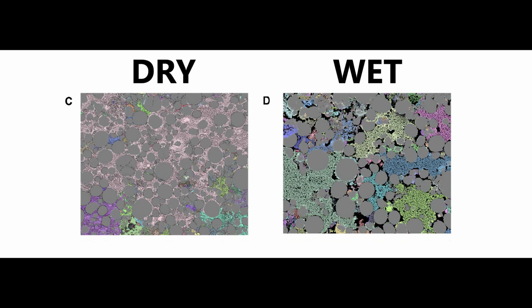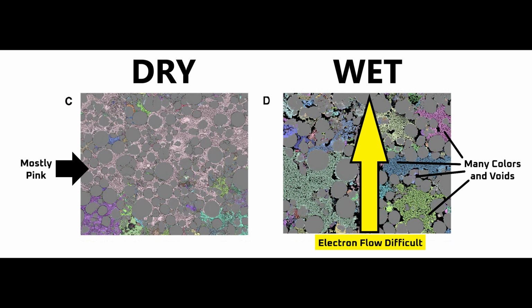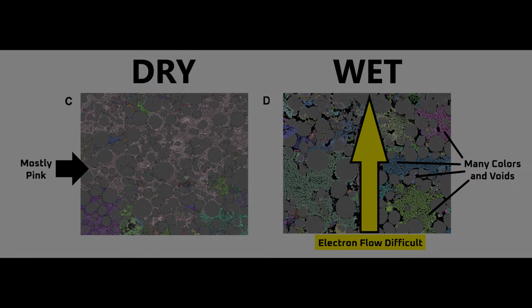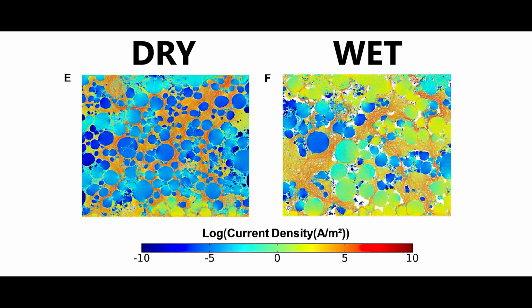Images C and D highlight that connectivity more explicitly. The cathode particles are in gray, and you'll notice multicolored pixels between them. All pixels of the same color share an electronic connectivity network. Image C for dry coating is mostly pink pixels, meaning electrons can travel almost anywhere in the electrode through the conductive network without having to pass through poorly conductive cathode particles. Image D for wet coating shows many colors and large black voids, meaning it's difficult for electrons to percolate through the cathode film. Image E and F are where it all comes together.